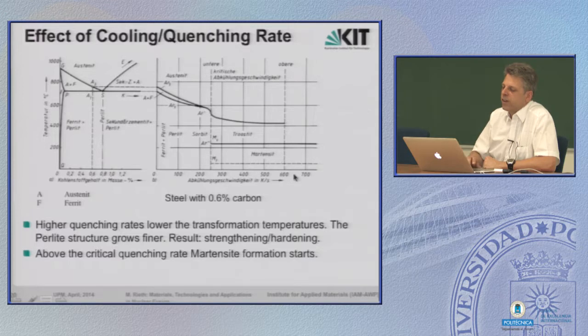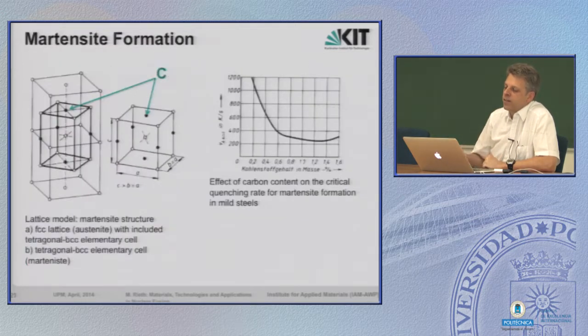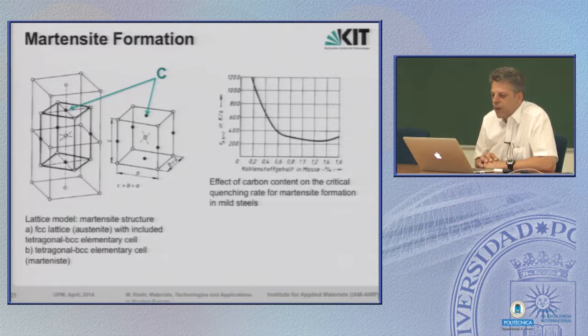If the carbon content is high enough, you quench it with a critical rate, you will end up in a phase which does not appear in the thermal equilibrium phase diagram, and that's martensite. What is martensite? There is a very simple model to show this, but then again it's not so simple.